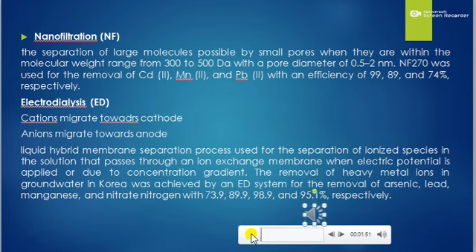For example, nanofiltration, the separation of large molecules possible by small pores when they are within the molecular weight range from 300 to 500 Dalton with pore diameter 0.5 to 2 nanometer. NF270 was used for the removal of cadmium, manganese and lead with an efficiency of approximately 99, 89 and 74%.